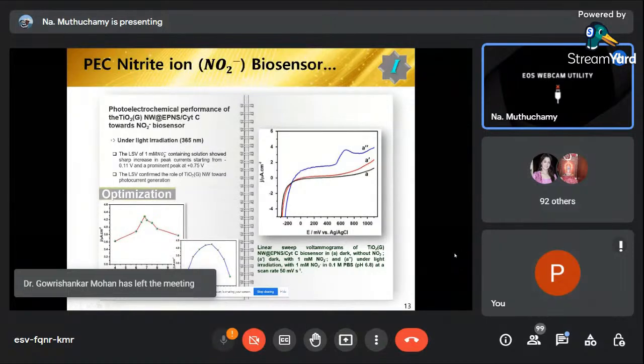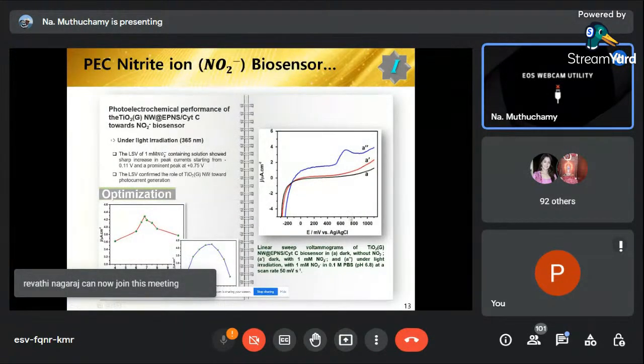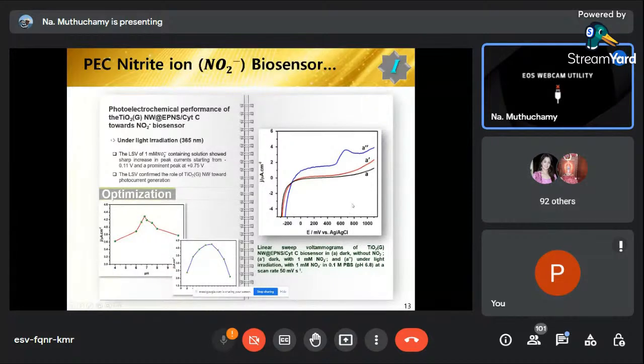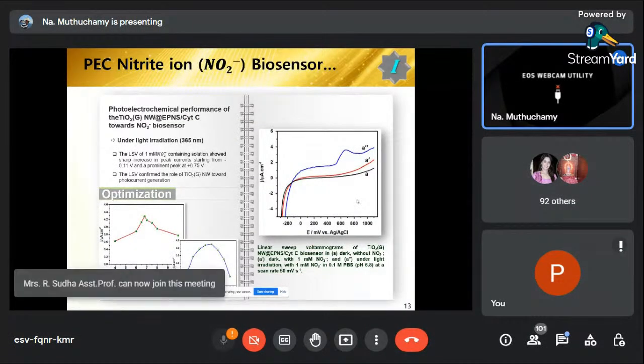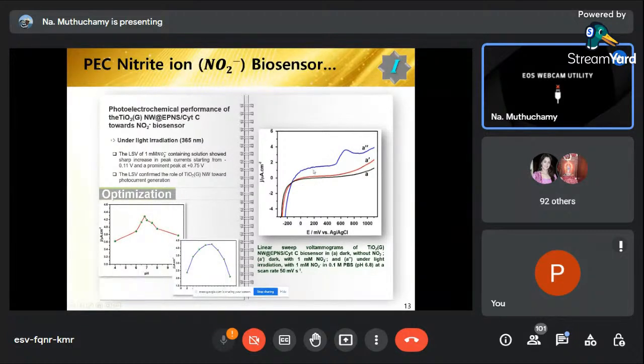So here you can see, without light and with light, the photo-enhanced current is noted at around 700 millivolt. So it shows that nitrite ion sensing happens around 700 millivolt. But when it's coupled with the bias potential, we can see that around 0.1 volt it enhances the current. So we have two potentials: one is the oxidation potential, and the other is the enhanced potential. Might be that the bias potential is helpful for first adsorbing the nitrite ion, then it oxidizes at 0.7 volt.